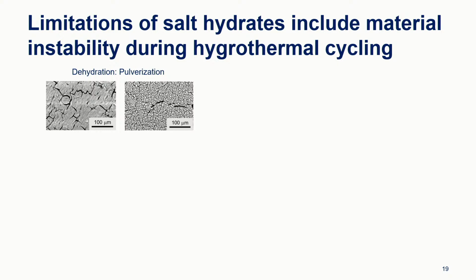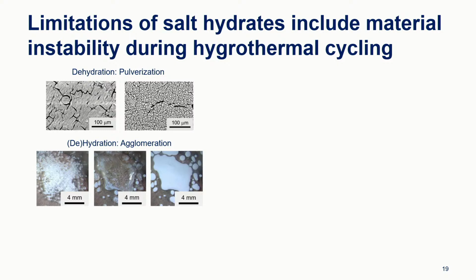Some of the challenges we have to be wary of are that when we dehydrate the salt, as the salt is releasing its water, it can pulverize, which means that it is just going to crack into much smaller particles, and that's because of these thermal stresses as the salt is releasing and absorbing the water into its crystal lattice. We could also see other challenges such as agglomeration. So rather than individual salt particles, if your relative humidity is too high or if your temperature is too high, you melt the salt hydrate and you get this agglomerated material,